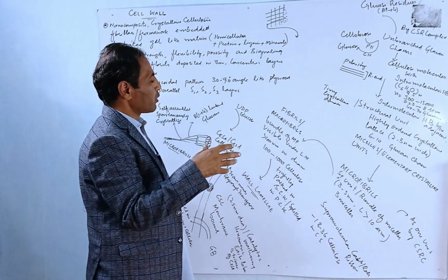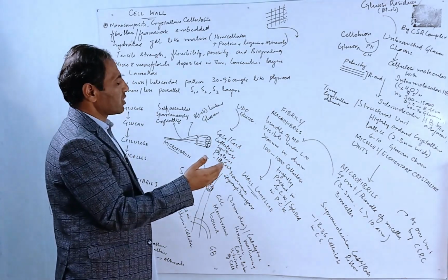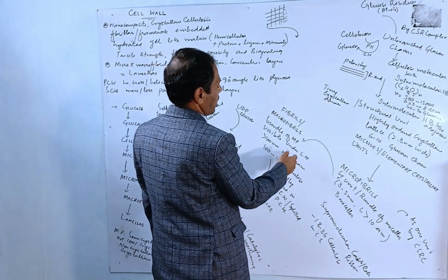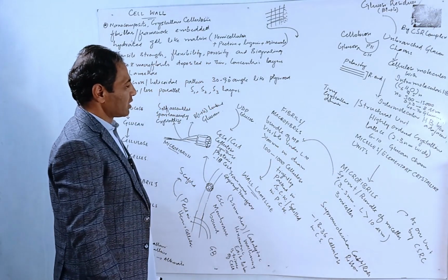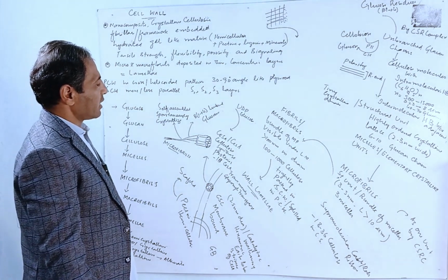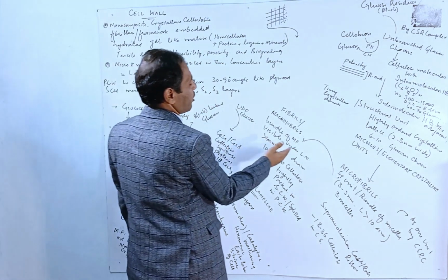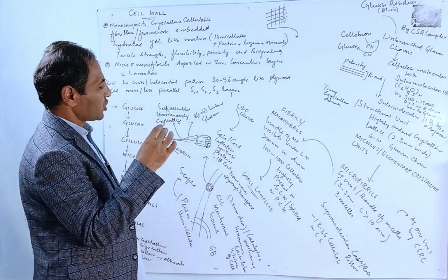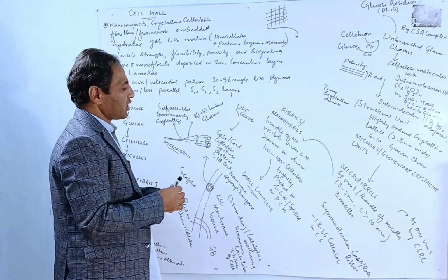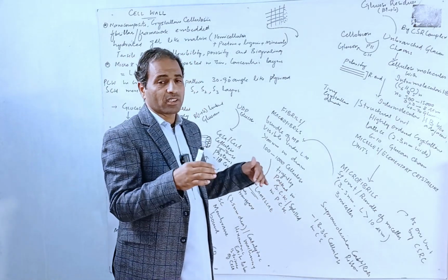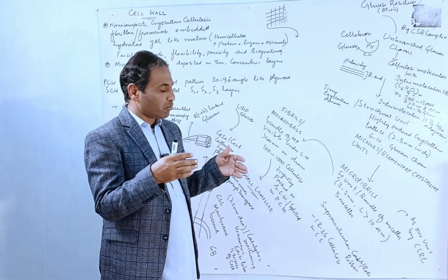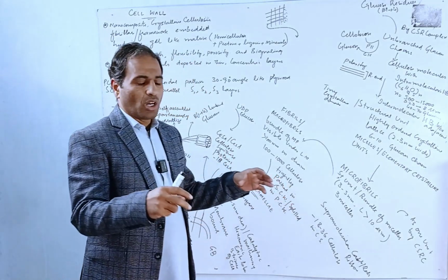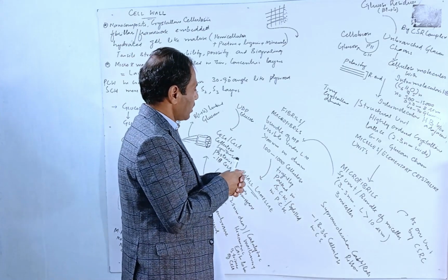Fibrils are bundles of microfibrils, which contain several hundred cellulose chains. From 100 to 1,000 cellulose chains can be found in a single macrofibril, which is more than 100 nanometers in diameter and a big structure. It is very tightly packed in the secondary cell wall and has a split arrangement or organization in the primary cell wall due to cell wall expansion.